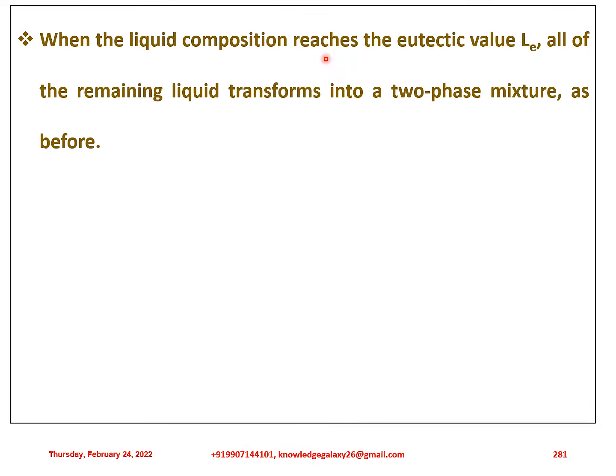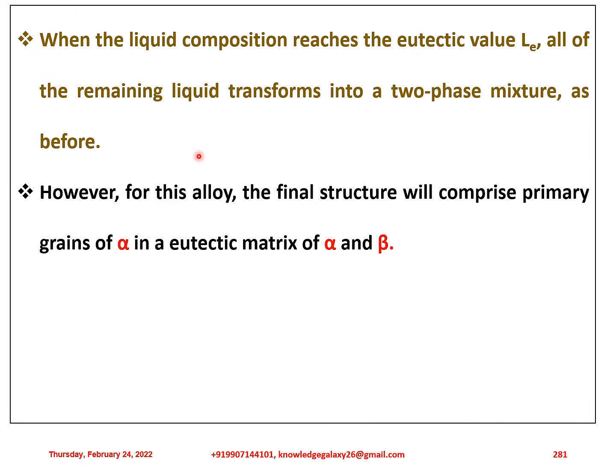When the liquid composition reaches the eutectic value L eutectic, all of the remaining liquid transforms into a two-phase mixture as before. However, for this alloy, the final structure will comprise primary grains of alpha in a eutectic matrix of alpha and beta. I hope it is very much clear to you all.